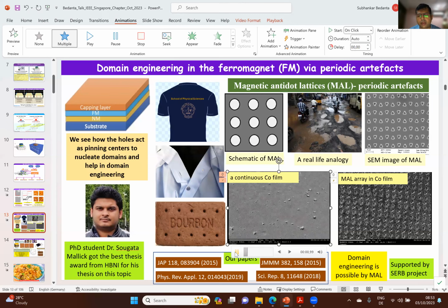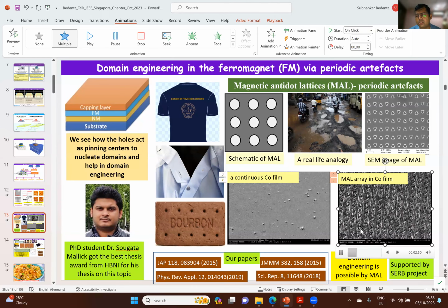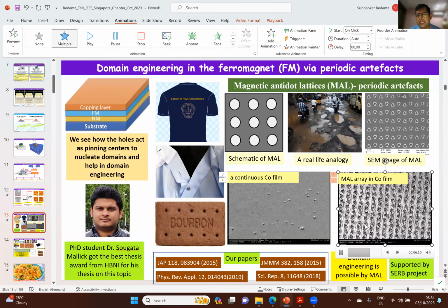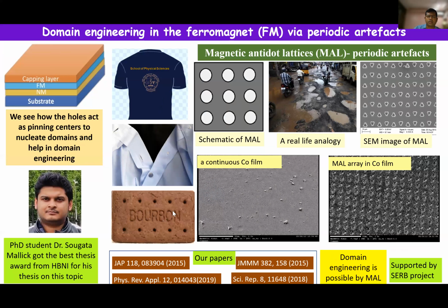Okay, so this is a ferromagnetic domain in a continuous thin film, and you see huge magnetic domains. I'm sorry for the small scale, but it's 100 microns. But now if you take the same film and dig these holes, these rectangles are basically holes in the continuous film, you see the domain size becomes smaller. That is domain engineering via these antidots, and that's very interesting. We have done much work, and there's a student who did his PhD on these magnetic antidot arrays, and there are several papers from our group on this.